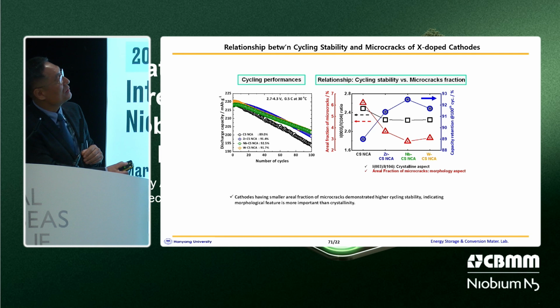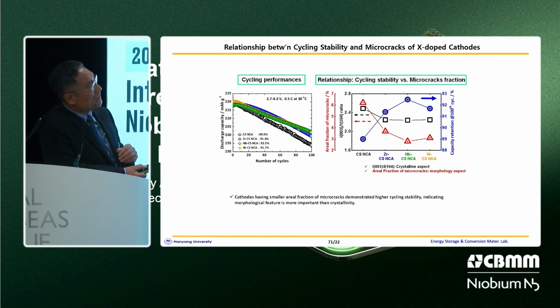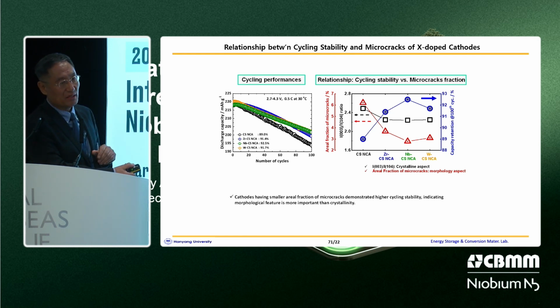And this is the relationship between the cycling stability, the microcrack fraction, and the crystallinity. This is the baseline, the zirconium, niobium, and tungsten-doped material. As you can see here, the cathode having the smaller areal fraction of microcracking demonstrates higher cycling stability, indicating morphological feature is more important than crystallinity. Based on this result, the niobium-doped cathode shows the best cycling performance in half cell testing.